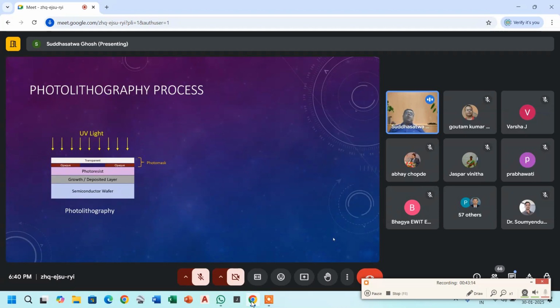Now, I would start a bit more detailed on the photolithography process. We have briefly mentioned it in the past, but now I will go a bit deeper. As I mentioned here, in photolithography, the wafers are covered with photoresist while spinning, and then we form a uniform layer of photoresist on a semiconductor wafer. On top of that, we use a photomask, which is basically a transparent material with some opaque portions on it.